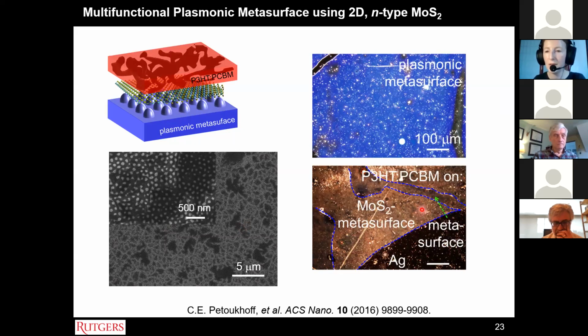So you can see, for example, in the presence of the MoS2 on the metasurface, we see greater light scattering due to the presence and the interaction of the MoS2 with the metasurface. This is the image of the actual semiconductor on the MoS2 on the metasurface. And you can see without the MoS2, there's not quite as good scattering. So clearly the MoS2 is enhancing the scattering as well.